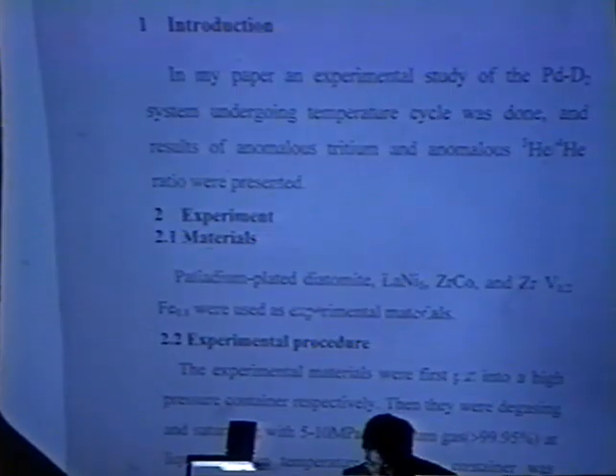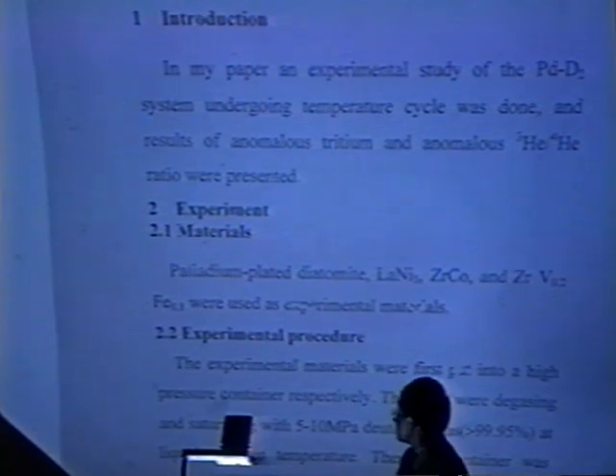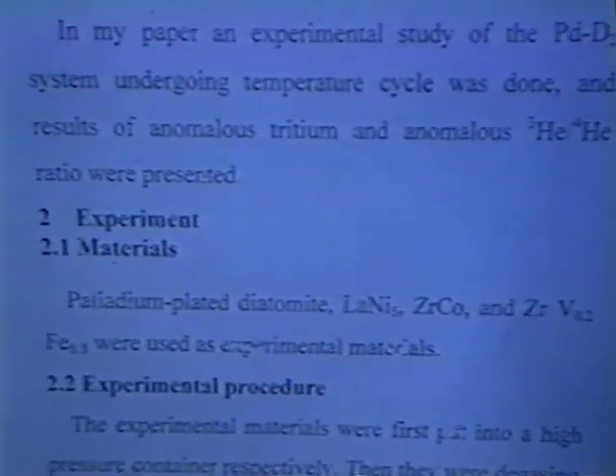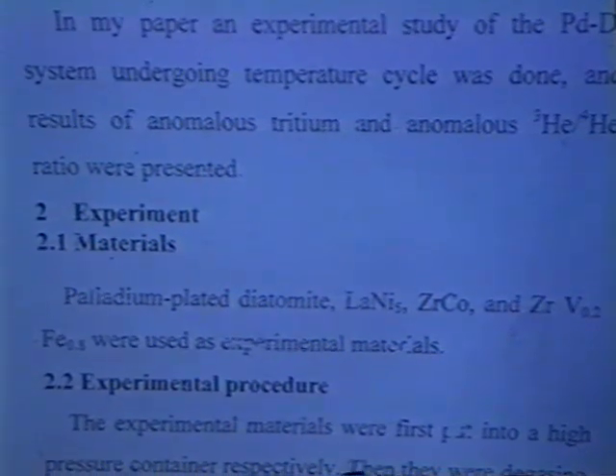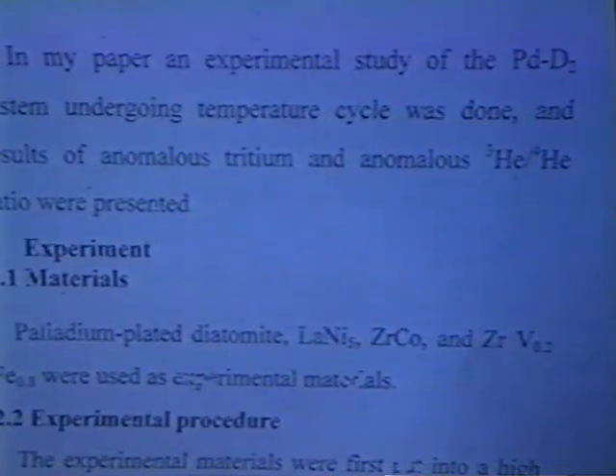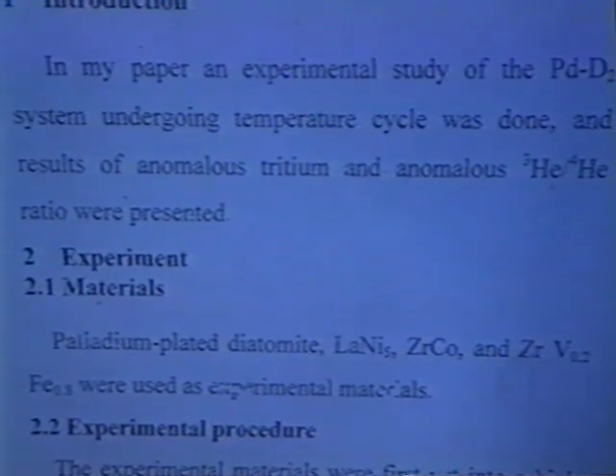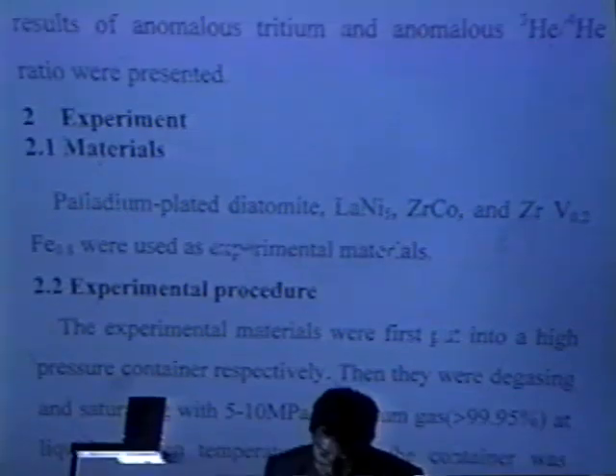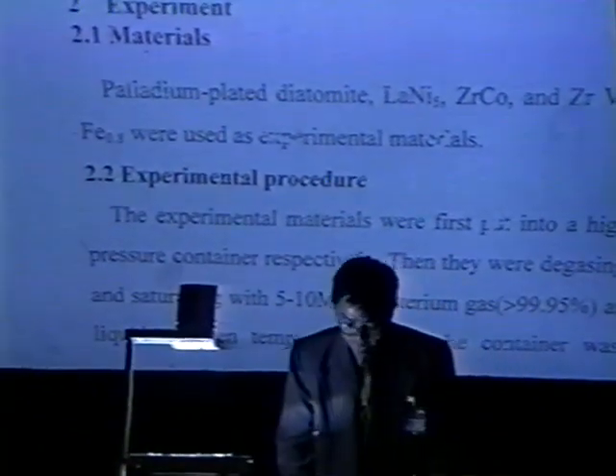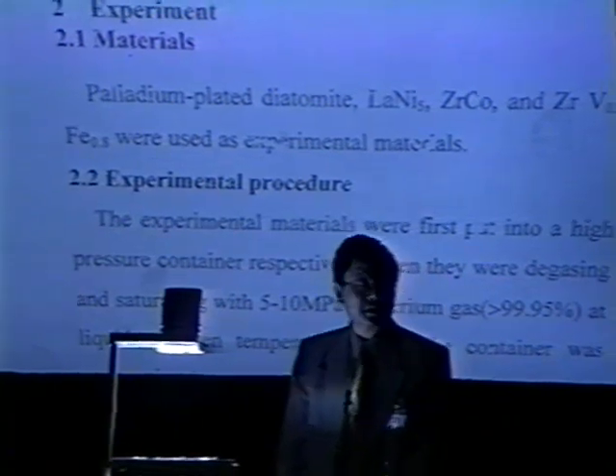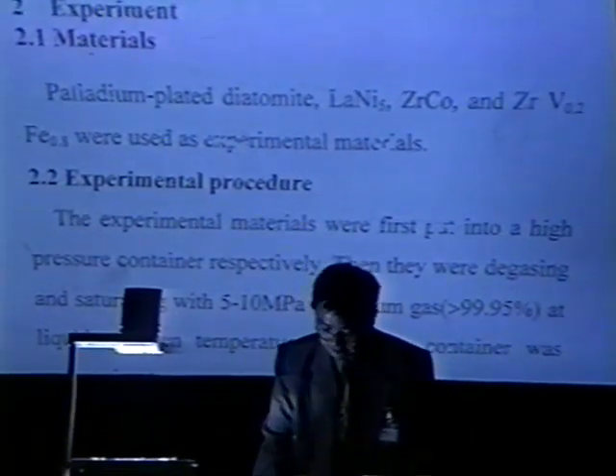My paper is on an experimental study of the anomalous nuclear reaction in palladium deuterium systems. In my paper, an experimental study of the palladium deuterium system undergoing temperature cycling was done, and the results were presented. Experiment. First, materials. In our experiment, palladium plated diatomite and then LaNi5, ZrCo, and Zr V0.2Fe0.8 were used as experimental materials.